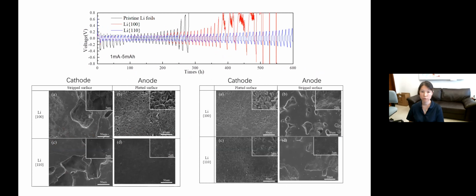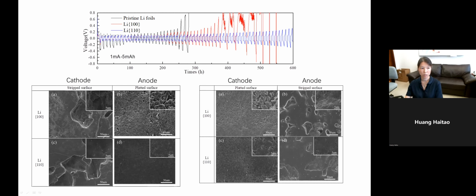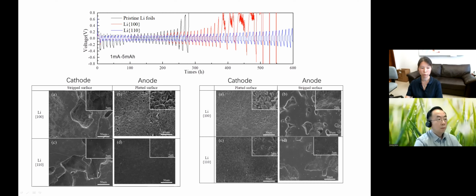But then an interesting piece of result I'd like to show you is that if we carry out the cycling at a high capacity of 5 milliamp hour for the symmetrical cell, of course, the performance would decay at large capacity. But still, the lithium 110 is the winner to the last. It performs a lot better than the pristine sample, the lithium 100 sample, right? But if you look at the surface, for both lithium 100 and 110, at such large capacity, on the cathode side, when stripped, the pit will be formed. But this pit on the lithium 110 did appear to be much shallower than that of the lithium 100. But then it does form.